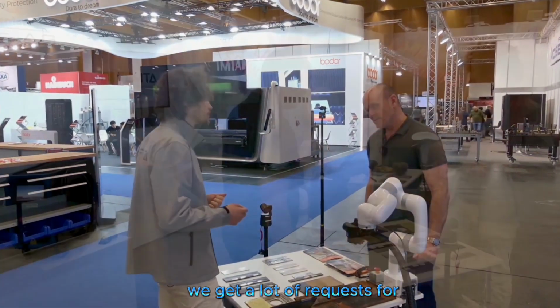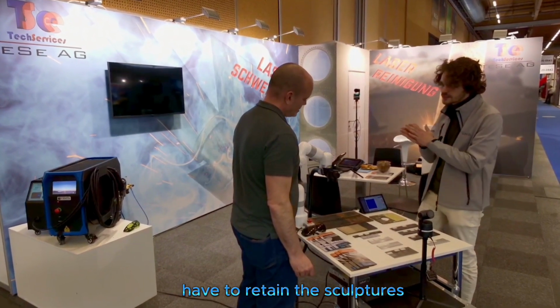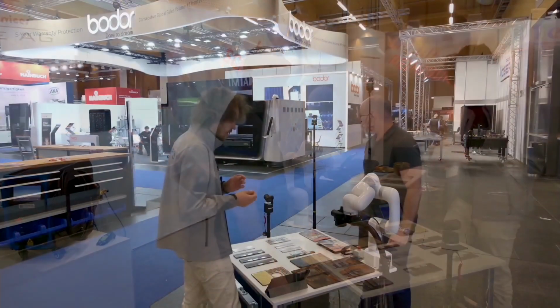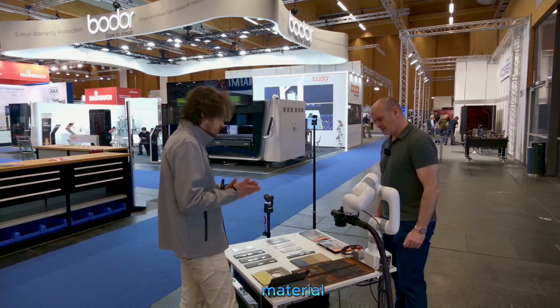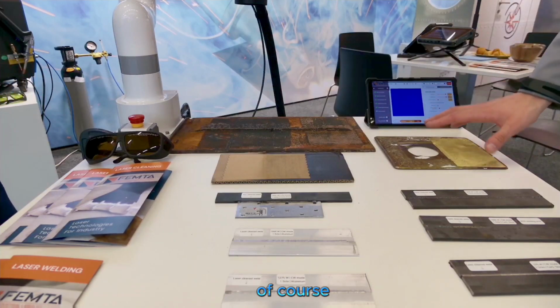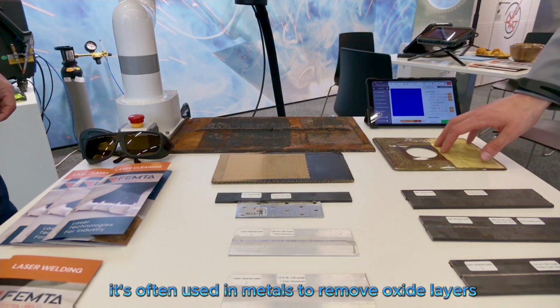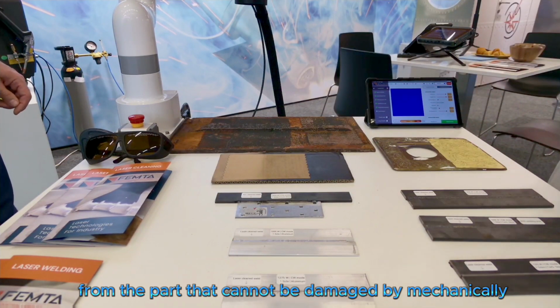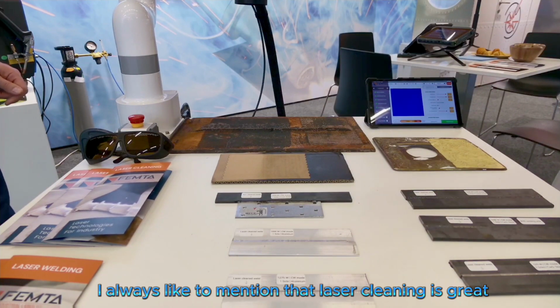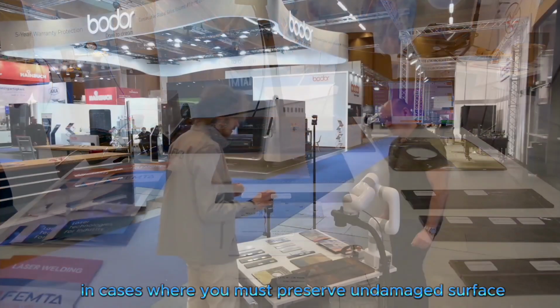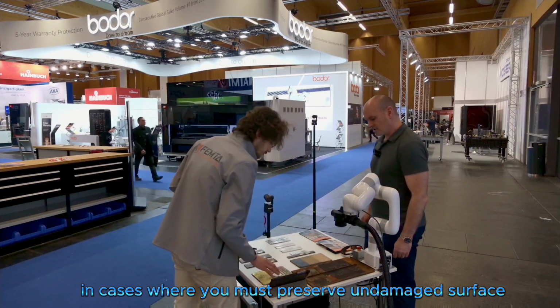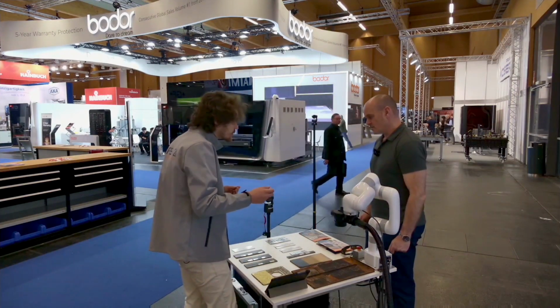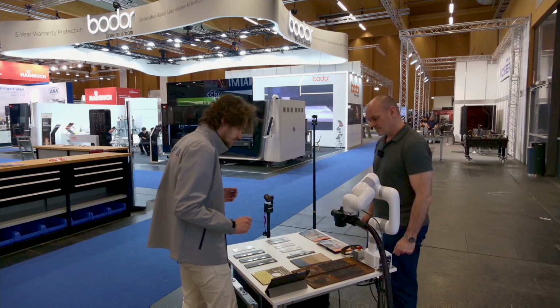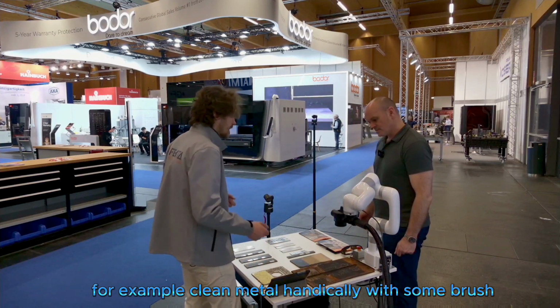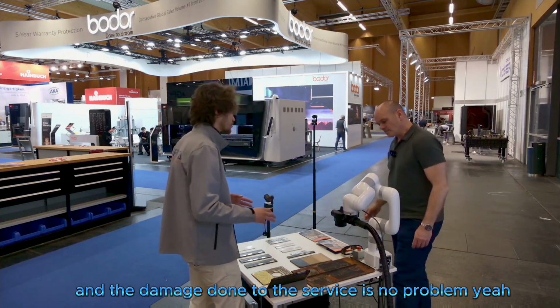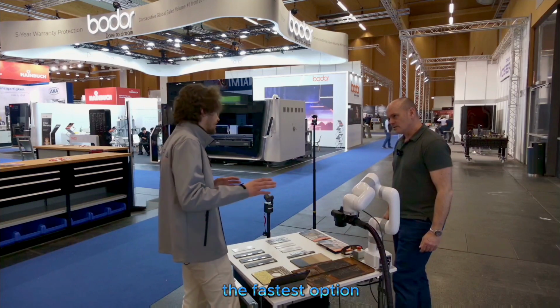Wood, for example, is really common. We get a lot of requests from wood restorers because they have to repaint sculptures, and it's possible to remove paint without damaging the base material. So it's one of the best technologies for that. Of course, it's often used on metals to remove oxide layers or to remove grease from engines, from parts that cannot be damaged mechanically. I always like to mention that laser cleaning is great and ideal in cases where you must preserve an undamaged surface. For example, for metal cleaning, it would be mostly engine parts or maybe some other really fine details. But if you can, for example, clean metal mechanically with some brush and the damage done to the surface is no problem, laser cleaning might not be the fastest option.